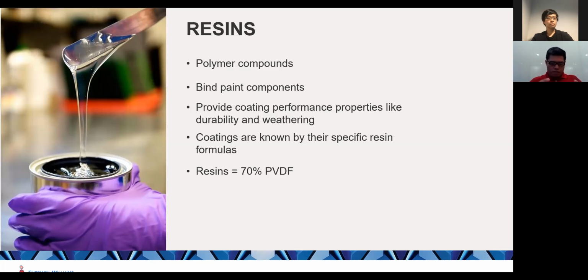And also, because I mentioned before, resin also provides the durability and the exterior weathering properties to the coating. So if the resin is not good, then we're expecting a lot of chalking happening over time because of the sunlight. The resin binder gets downgraded, causing chalking to happen. And it also protects the pigment from the sunlight as well, so to maintain the color of the finished good to stay as the original for as long as possible.